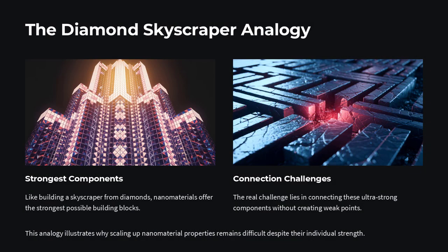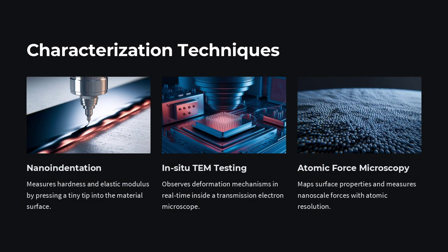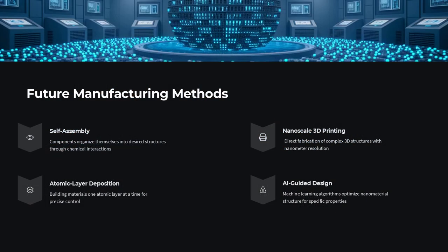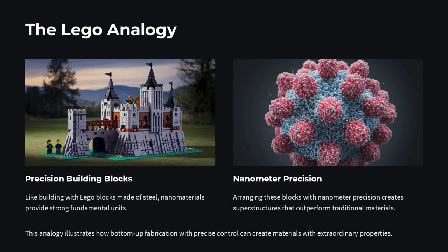Interestingly, the size-dependent strength paradox has been experimentally confirmed across a wide range of materials. Nanopillars of copper and nickel showing strengths near their ideal shear strength. Silicon nanowires surviving bending tests that would fracture bulk silicon. Graphene, a 2D sheet of carbon atoms, exhibiting record-breaking intrinsic strength, about 130 GPa, despite its atomic thinness.